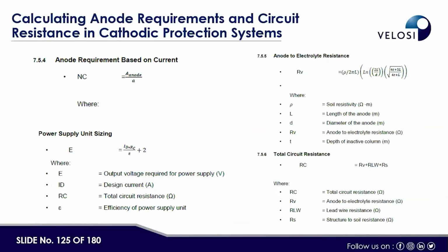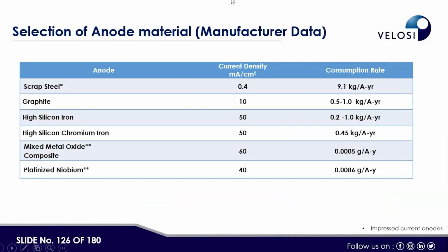Next. Then there are the different anodes, the selection of the anode, as we do the same in the sacrificial anode: magnesium, aluminum, or zinc. Here we use the impressed current anode system. This is the mixed metal oxide, which is most commonly used. It also gives the anode to electrolyte resistance, as we measured for the sacrificial anode in the case study. In the impressed current CP system, the most important is the anode to electrolyte resistance. There are different formulas for the different configurations of the anodes, whether it's the deep well anode, the horizontal anode, or a discrete anode. So different types of systems are used and different formulas are applied. Again, this slide represents what type of anode material is preferably used.